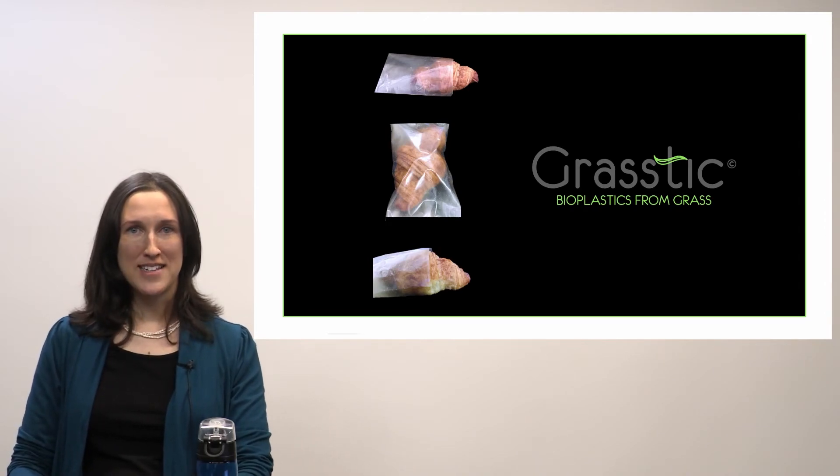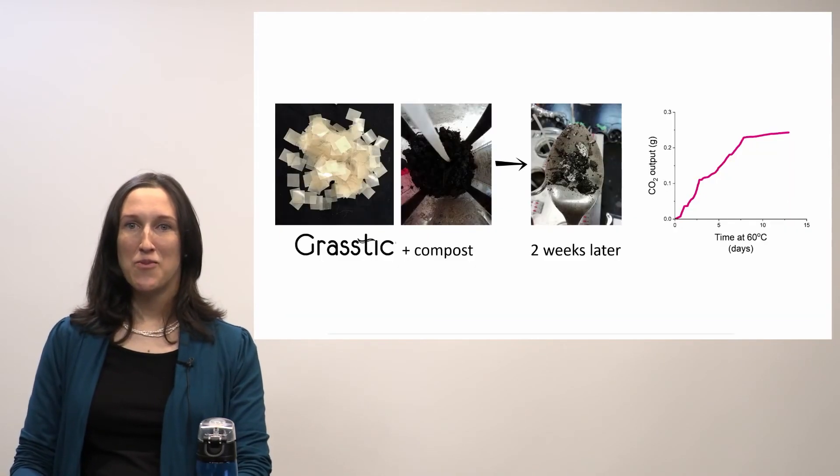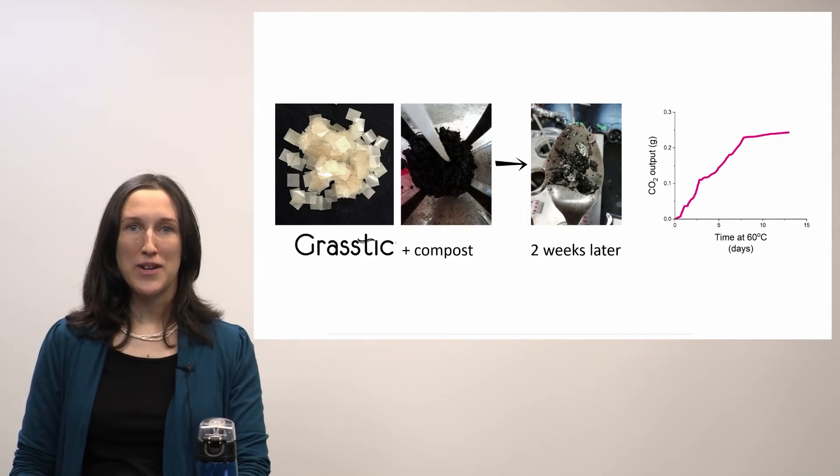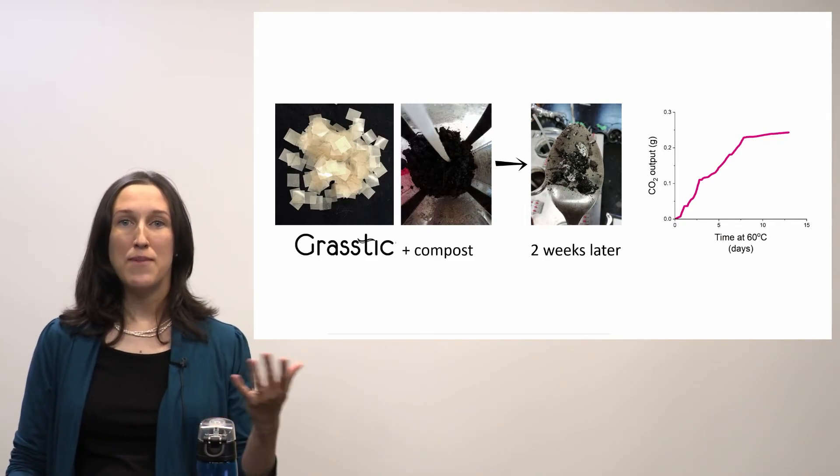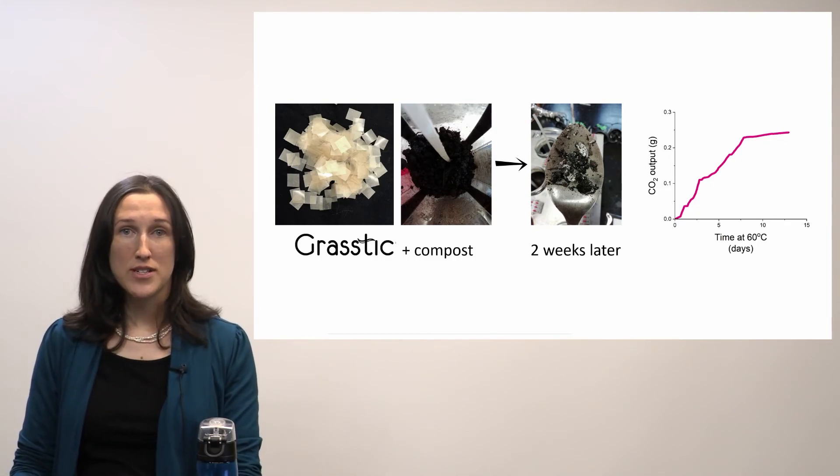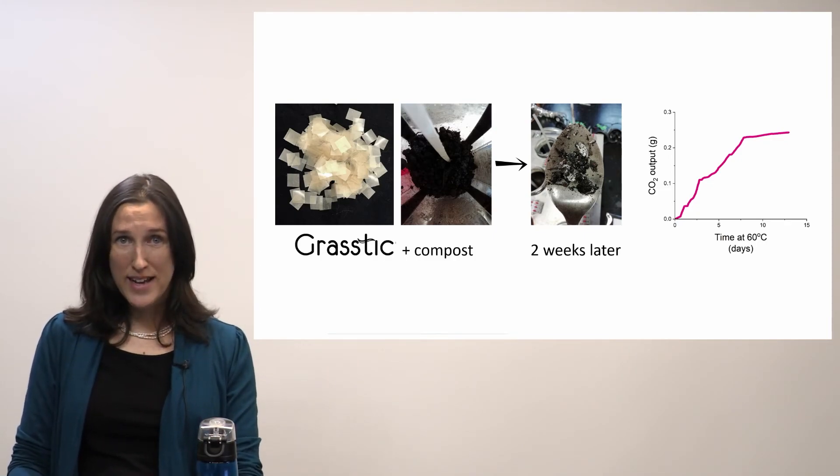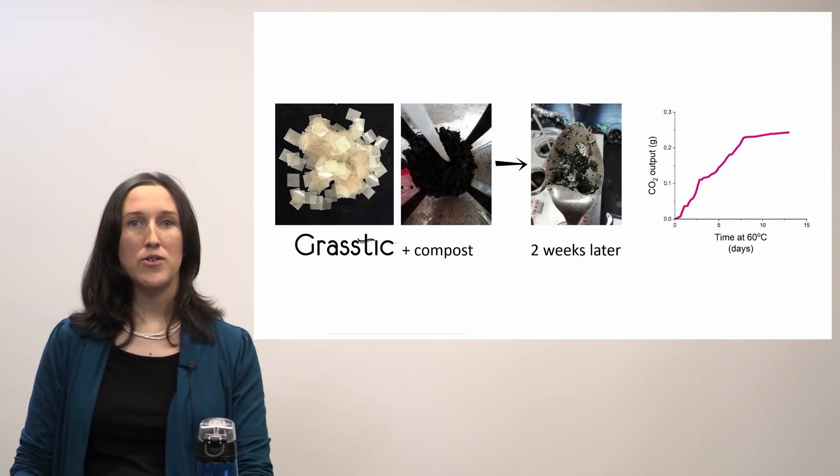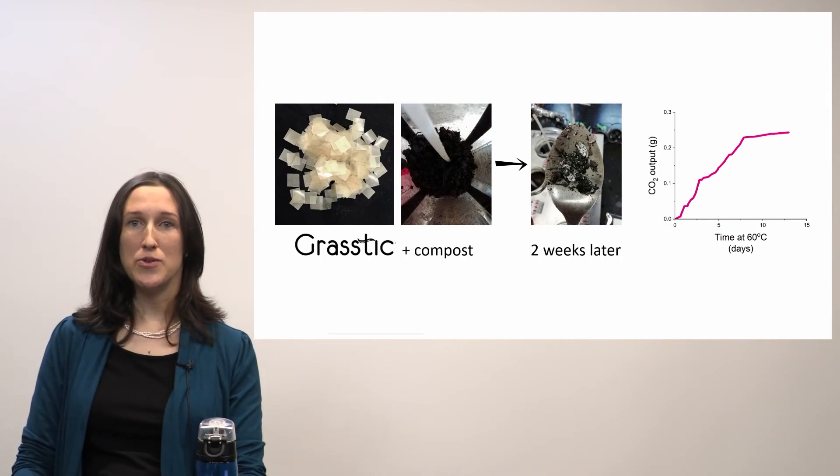So what's going on now with Grasstic in the lab? Well, we're currently testing its biodegradation, mixing Grasstic with soil and compost and measuring its degradation products over time. We've found that in about two weeks it seems to be completely biodegraded, and that's very good news.